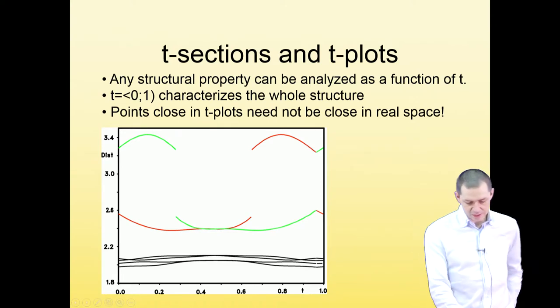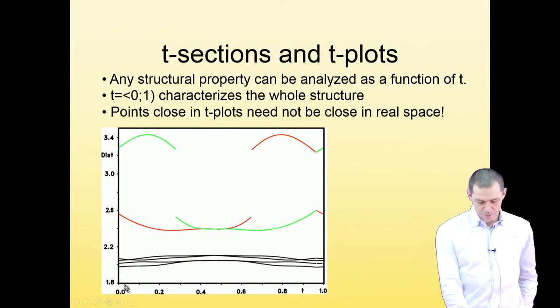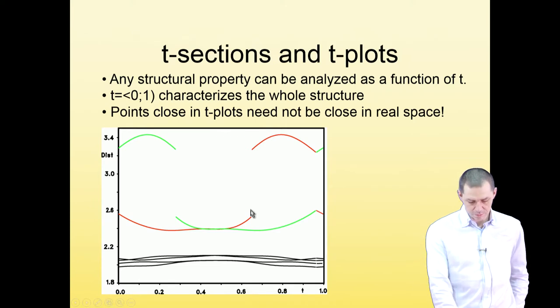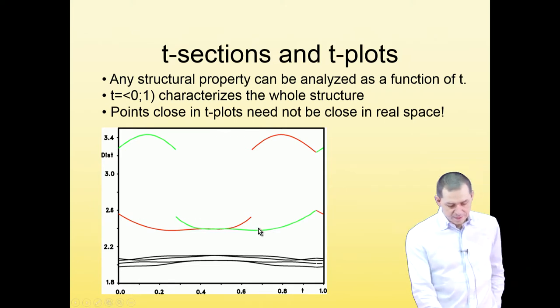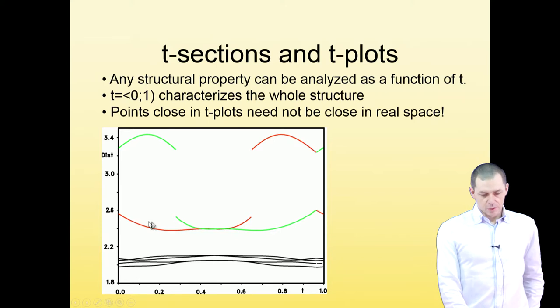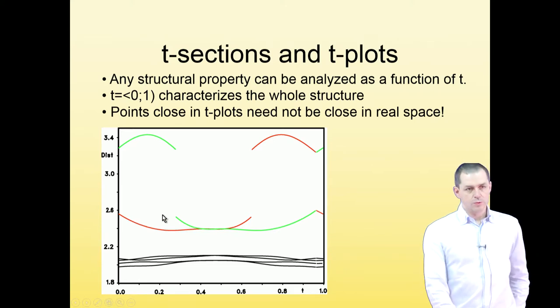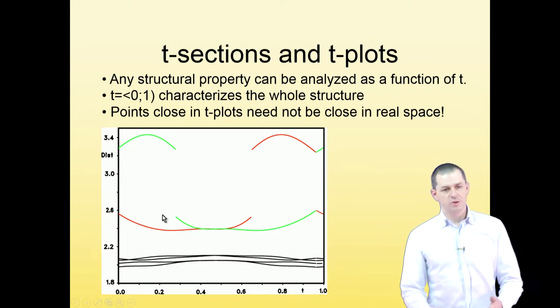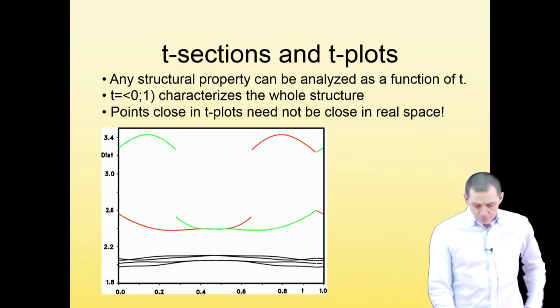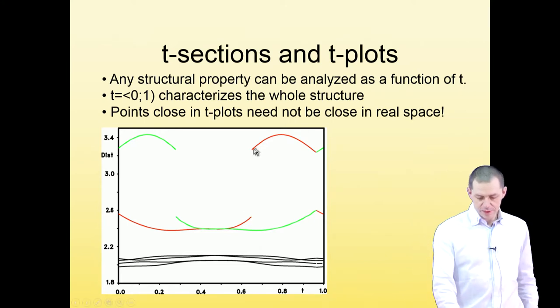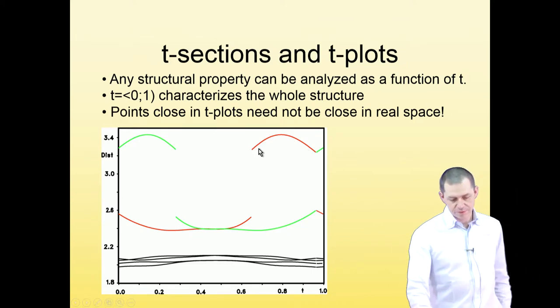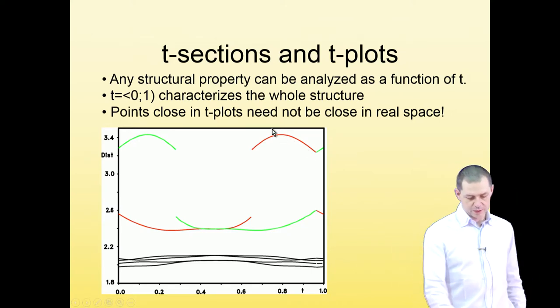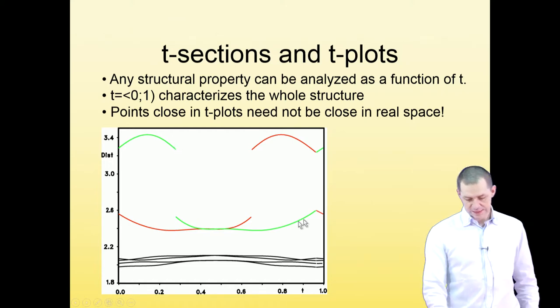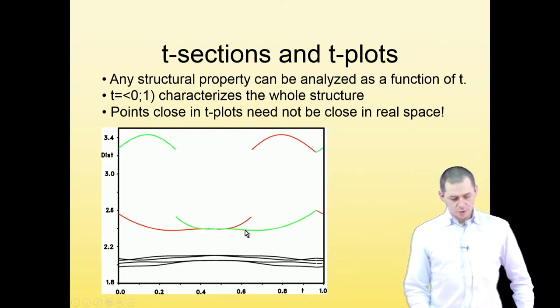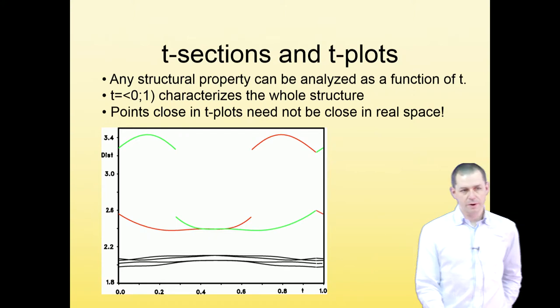So you see that in a certain part of the T interval, in about two-thirds, this oxygen atom, the red one, is relatively close to chromium, and you can say that it's coordinating the chromium. But then suddenly it jumps, and in another part of the T interval it is far from the chromium and it's not coordinating. And the green one does the same, it's symmetry related.